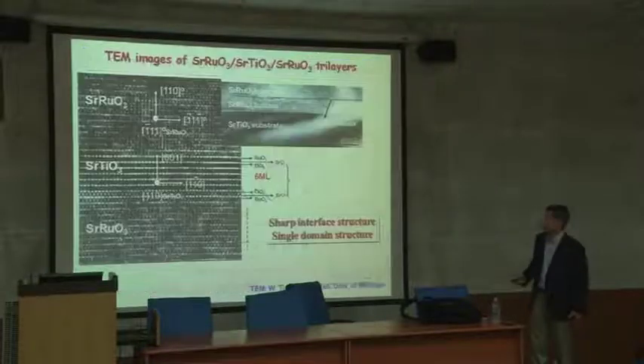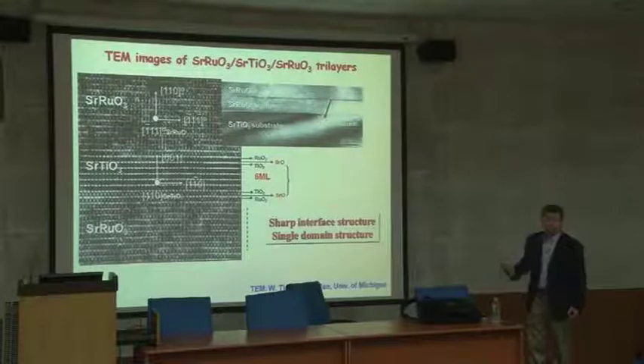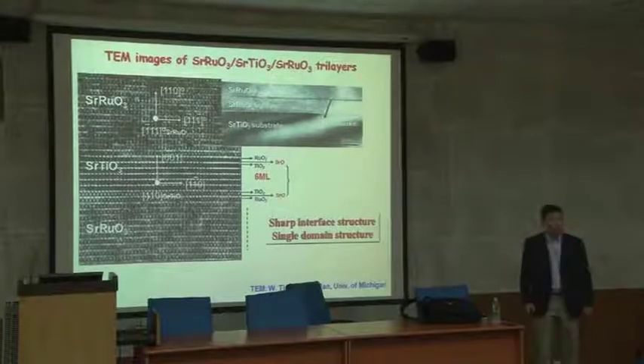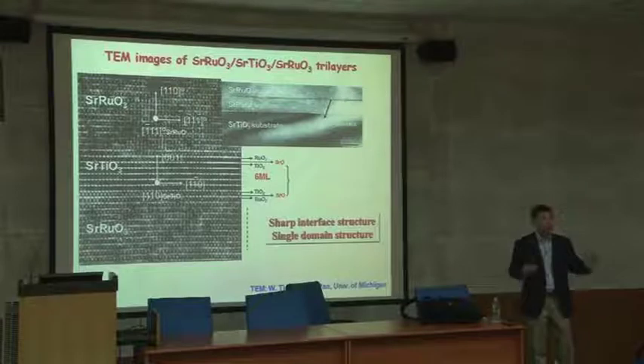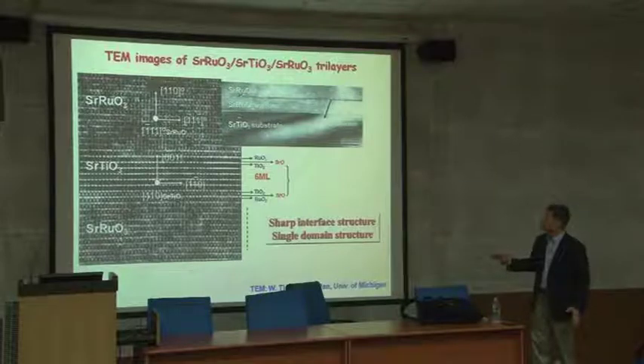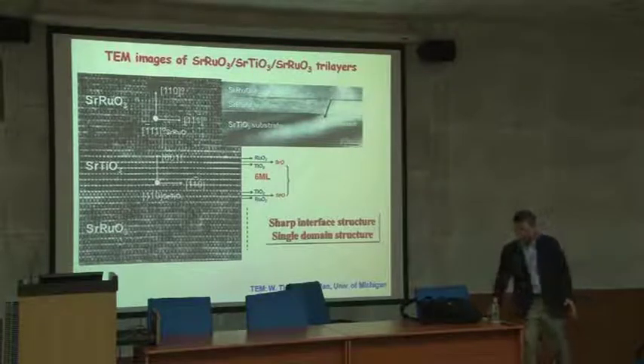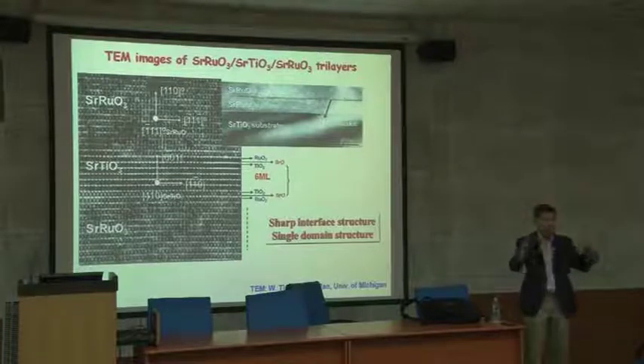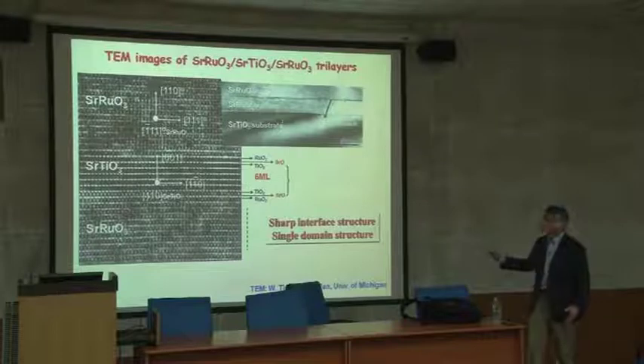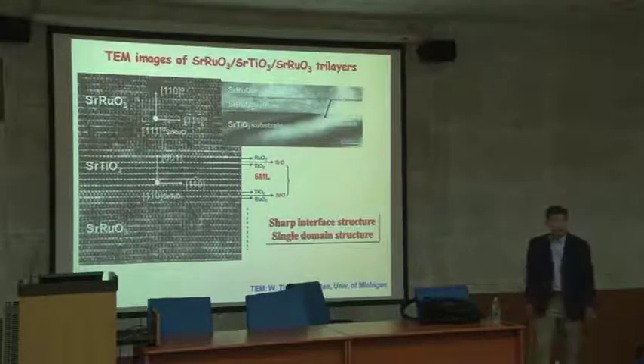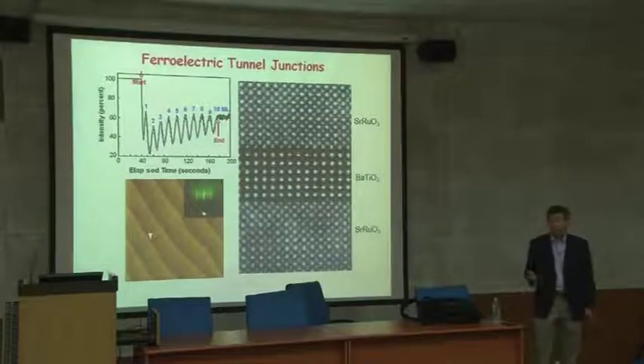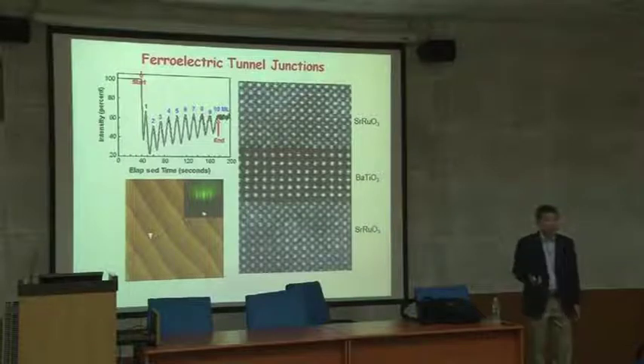And then when you look at the cross-sectional micrograph, all layers are perfect single crystal. And you can see there are no grain boundaries and no dislocations, which means fully coherent. And the lattice parameter of strontium ruthenate is larger than strontium titanate, so it grows biaxially compressed, and grows like this. And then the very thin layer of strontium titanate sandwiched between here, you can see that it's completely single crystal.